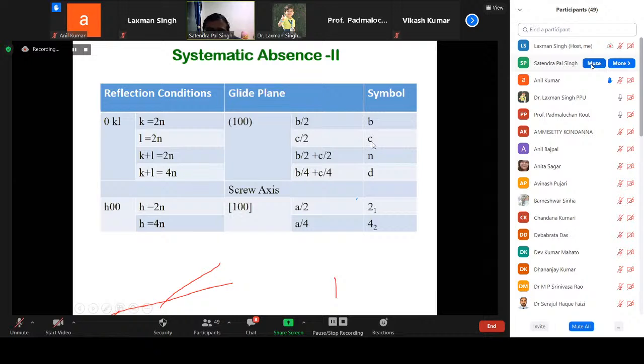So this is the b glide, this is called the c glide, this is called the diagonal glide, that is b/2 plus c/2, and this is called the diamond glide. So these are the glide planes. The glide plane is along 100, the translation is along b/2, and this is called the b glide. Similarly, we can have the screw axis. If H00 is even, the reflection condition is H00. So if H is even, then the screw axis is along that axis.